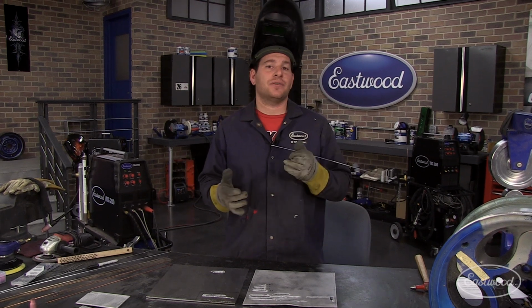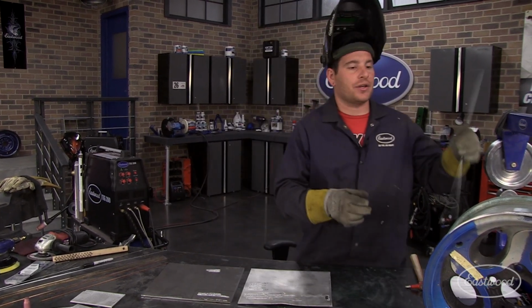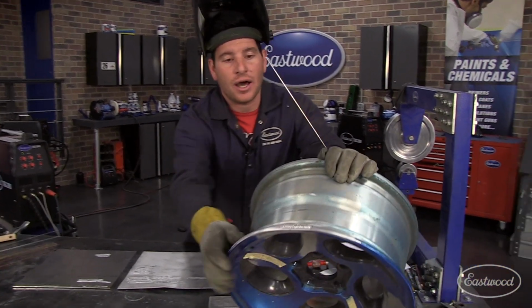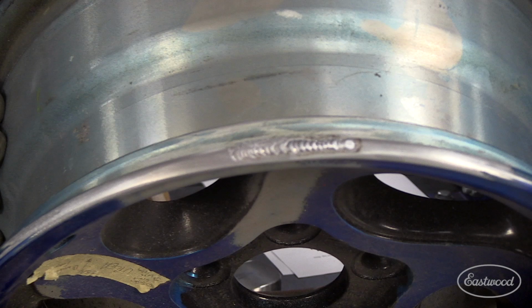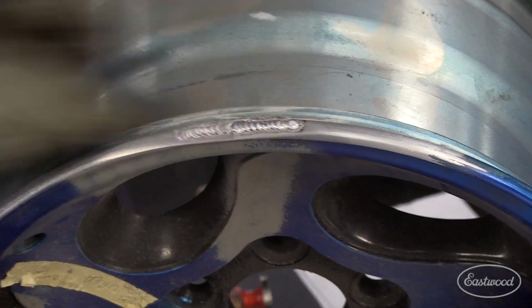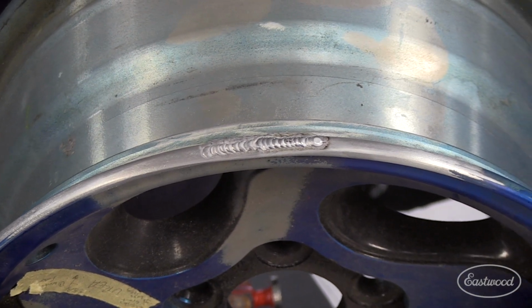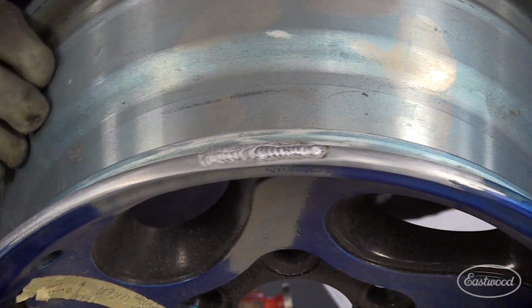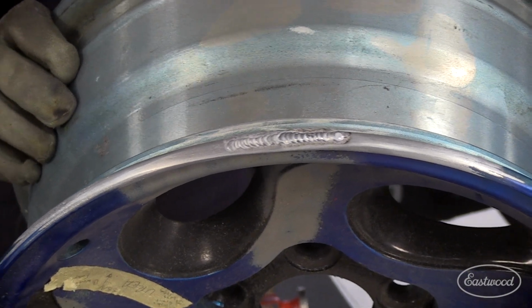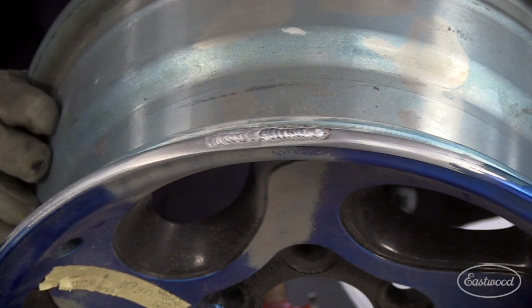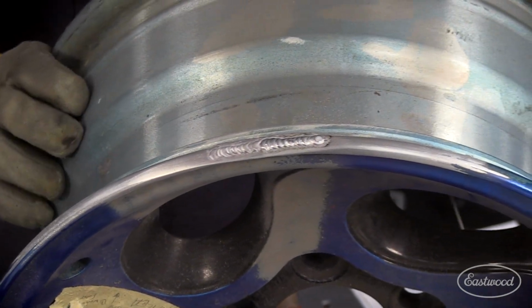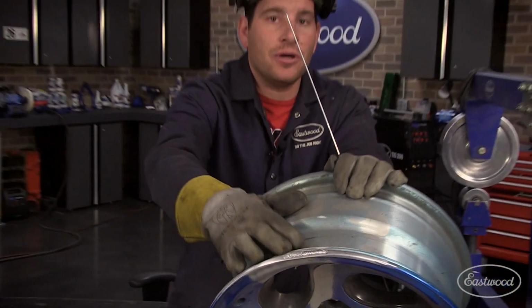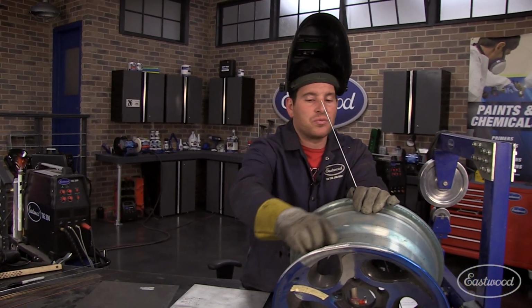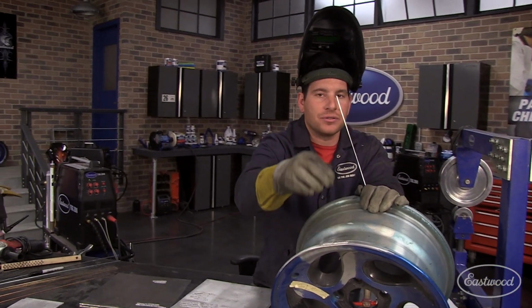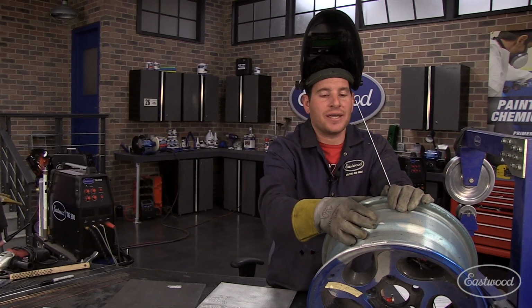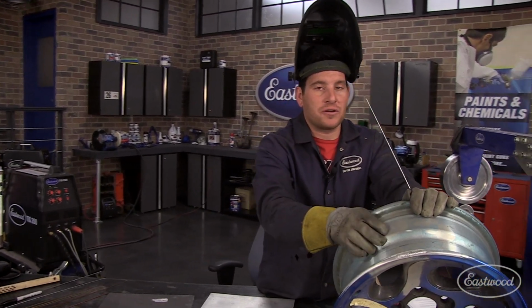So if it's something that's cracked or damaged, like this wheel here that I started doing a little repair on. This is an aluminum wheel that was cracked, or I'm sorry, curbed. Had a big curbed area, it's dipped down in here. So what you need to do is build that area back up. Now you can't just start welding right on that area that's been dragged against the side of a curb, because there's dirt in there, there's grime in there, and just from using the wheel in general, it's got all kinds of dirt in it. So what you need to do is sand down below the surface. This damage wasn't quite as deep, but I had to sand down below the deepest cut or damage in it to get down to clean, fresh aluminum before I started welding.